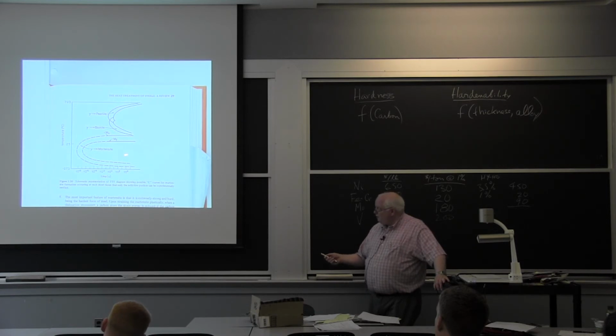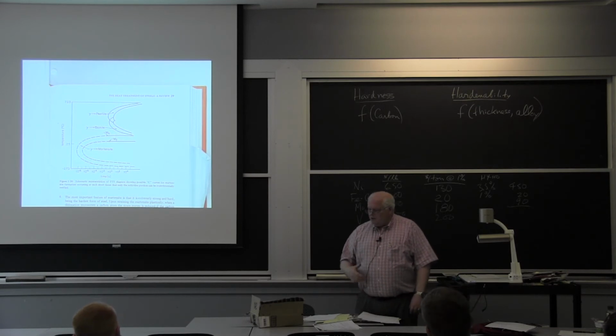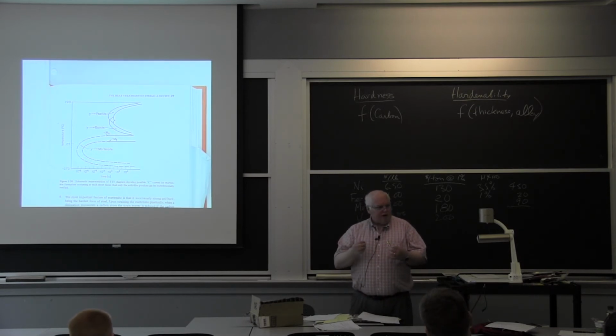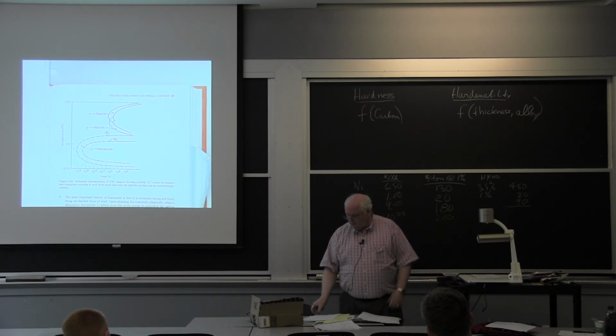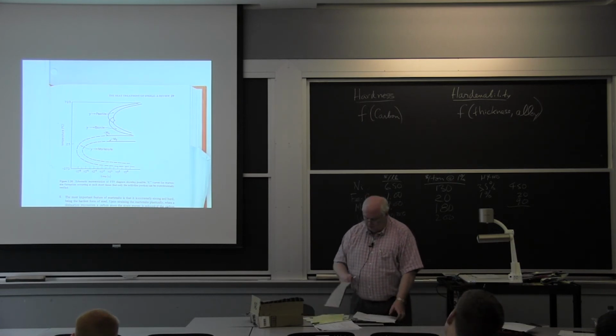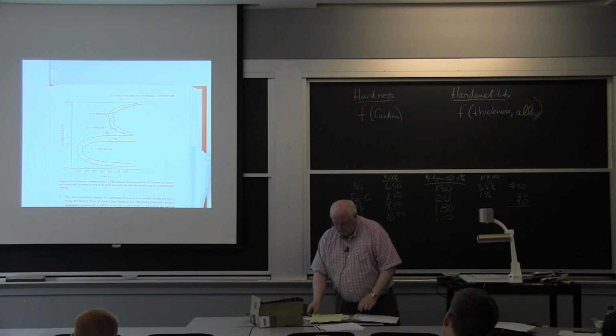Okay, this is the only time I've ever seen someone, in Charlie Brooks's book, where he actually put the nose of the martensite curve. I mean, ordinarily they go down 10 to the minus 1 or 10 to the minus 2 seconds, and they cut it off. He actually went down to 10 to the minus 8. And there is a scientific reason. It has to do with the martensitic transformation, which is what we call a displacive transformation. You ever heard about shape memory alloys, these nickel titanium alloys that you can make a wire out of, straighten out the wire, and if you've heat treated it properly and you heat it up a little bit, you can spell out your name. The wire has a memory. Well, dentists now use this for braces. It's a martensitic transformation in a non-ferrous alloy. So there are some uses for martensite in a number of areas, other than worrying about messing up the weldability of steels.